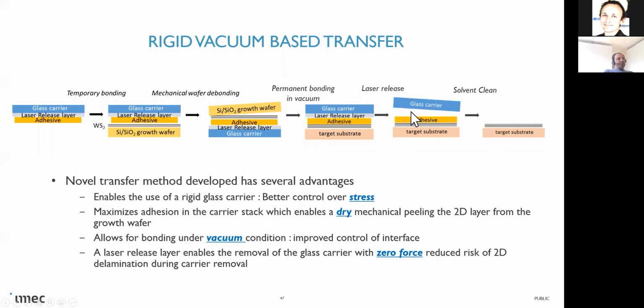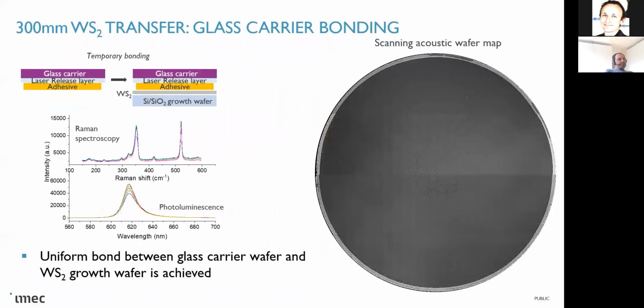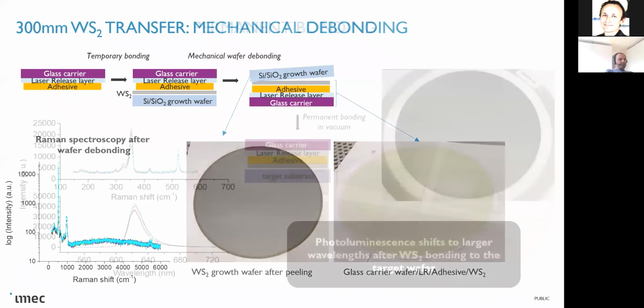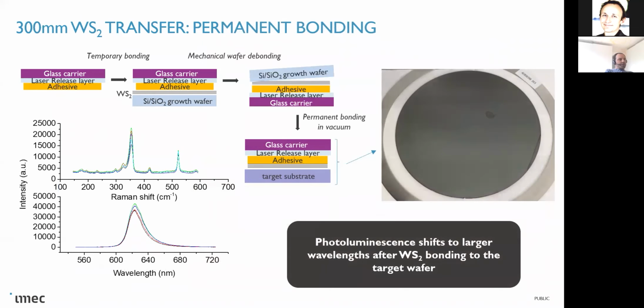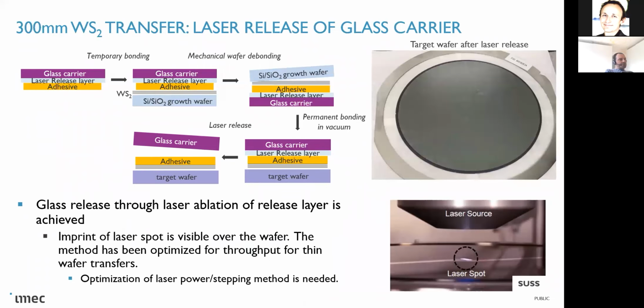The reason we are doing a laser release is because we are not inducing any force on the 2D material while removing that rigid carrier. So basically, it's again to try to control the strain in that whole sequence. And then in a wet clean, you can remove the whole adhesive layer. And this has been demonstrated at Imec. I will go very quickly over it. These are the different steps, and this is the laser release step.